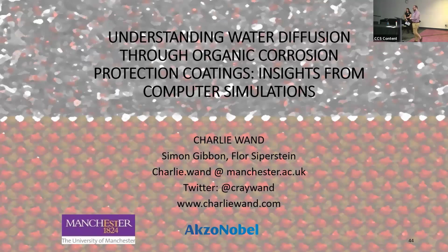Another more important thing is, models are great, and I'm really impressed with this, but they need to be validated against an experiment. Can you tell us an experiment that might validate your model? Yes, so there is, the word escapes me, PALS spectroscopy can help find the average pore size, which is the same as the free volume size I was talking about here. So we can compare them, and I think collaborators at Sheffield, Stephanie, have been looking at neutron scattering. I don't think she's here today. There's Patrick, Mr. Powell's over there.